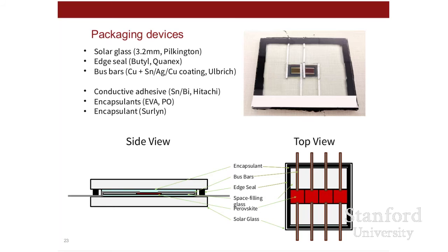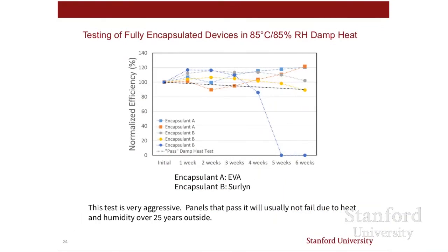And then when you do this, you can put it through a torture test that the solar industry uses to predict if something is going to last outside for 25 years. They test for 1,000 hours at 85 degrees Celsius and 85% humidity, which is a really aggressive test. And we did that, and one of our 3 packages failed. It leaked and water got in, but 2 of them didn't, and we passed this test. After 1,000 hours, actually the efficiency increased. And so this is extremely encouraging that we passed that test.